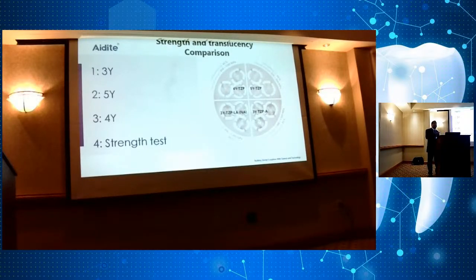By the way, a lot of these figures are exaggerated. I can tell you that from experience, because when I used to do the slicing and dicing and testing, I would find that they don't use the protocols for testing. They actually make their own testing. And because we don't have ISO standards written for this material, they will take 10 pieces, they'll break them, and they'll get a result from the 10 pieces. The ISO standard states that you should always use 30 pieces.